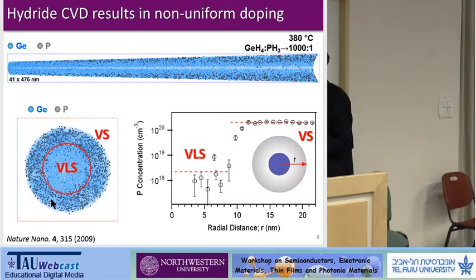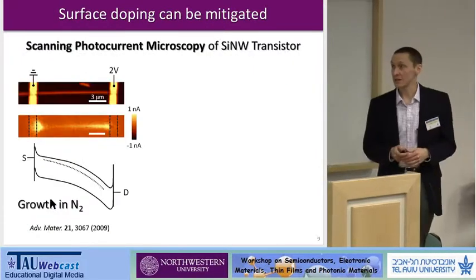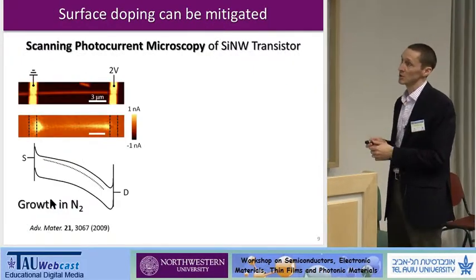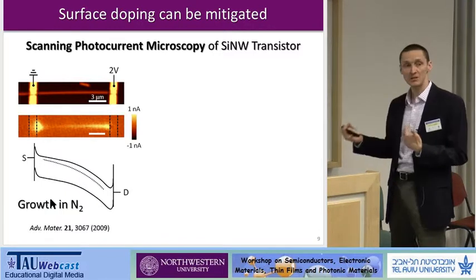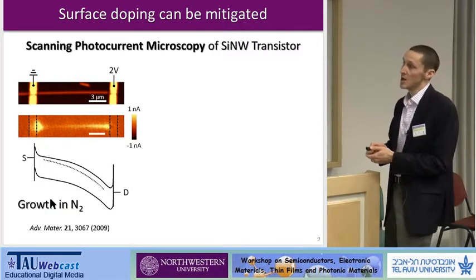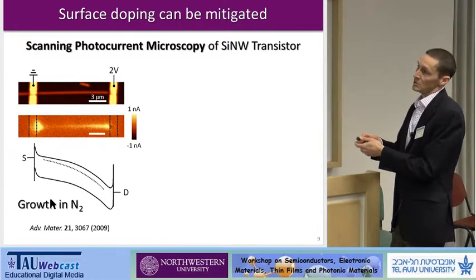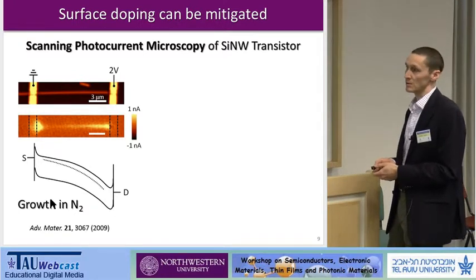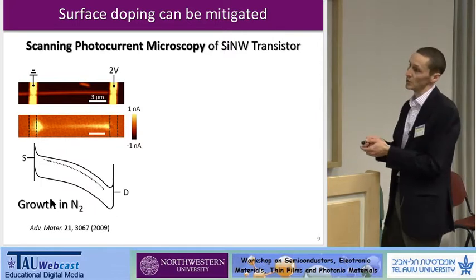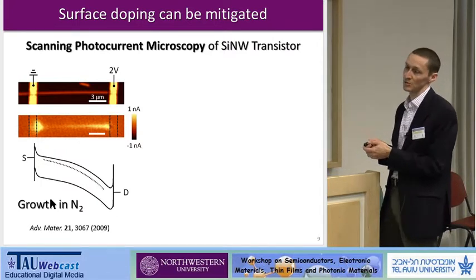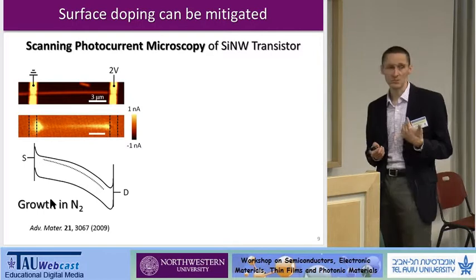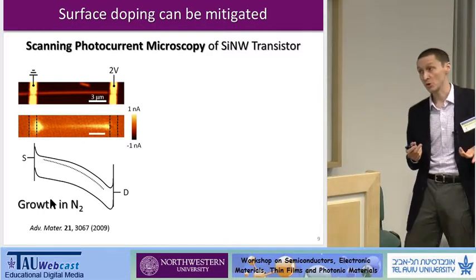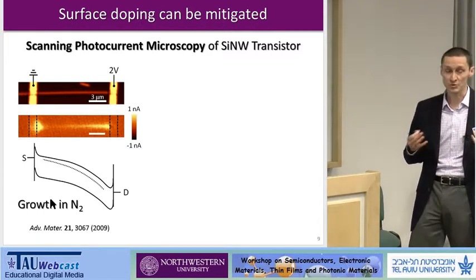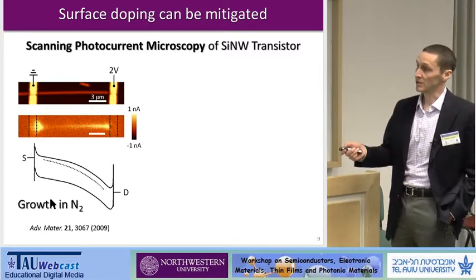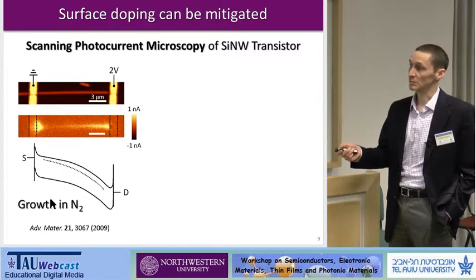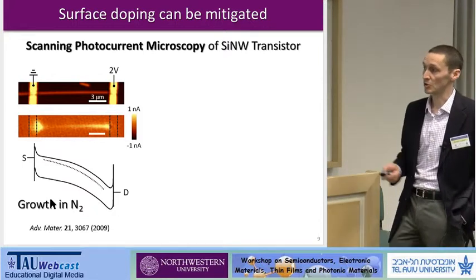Now to see that on the functional side, there's a couple approaches one can take. One is scanning photocurrent microscopy, which we did in our group. So now we're looking at silicon, but the same phenomenon occurs. This is an optical microscope image, and below this is an image of the photocurrent. Okay, so without going into great detail, what you see in this non-uniform channel response is essentially a variation in resistivity. The brighter regions where you're getting more photocurrent are more resistive, so they're more responsive to illumination. And it's telling us that the potential drop is not uniform. We're getting a greater potential drop here in the less doped region.